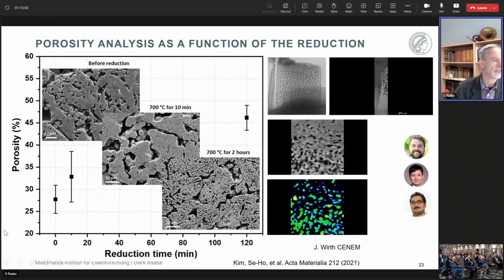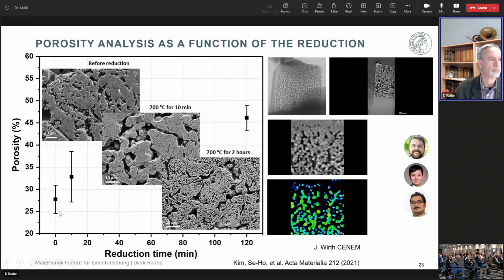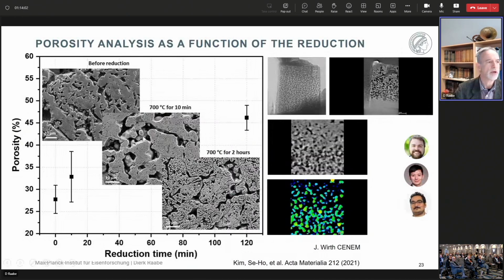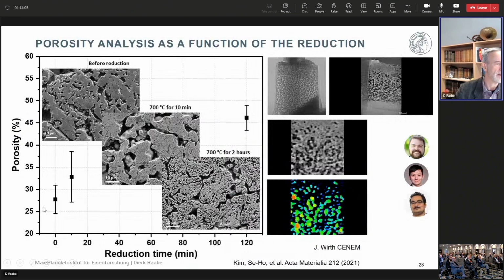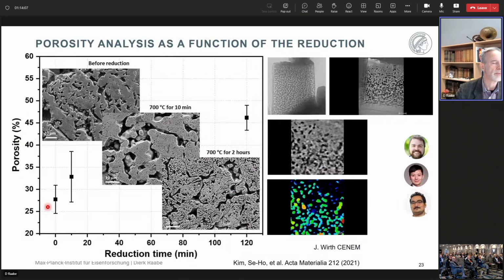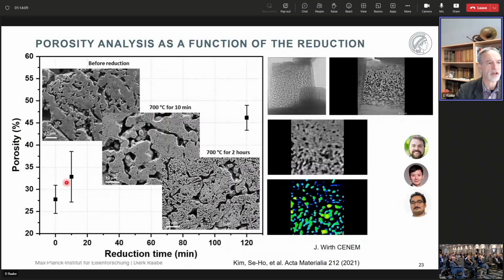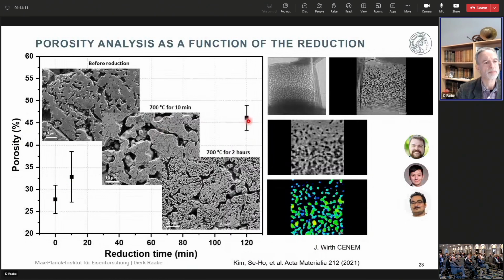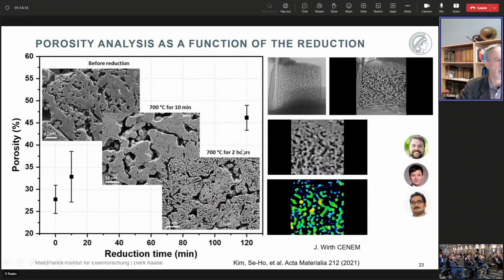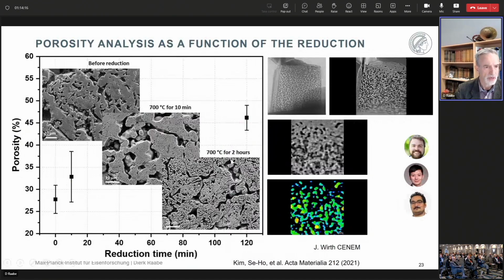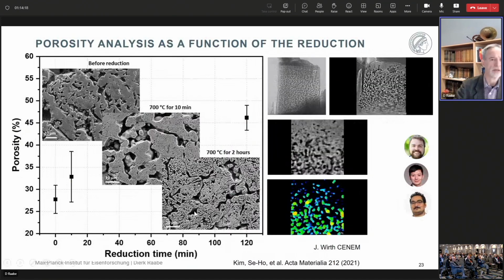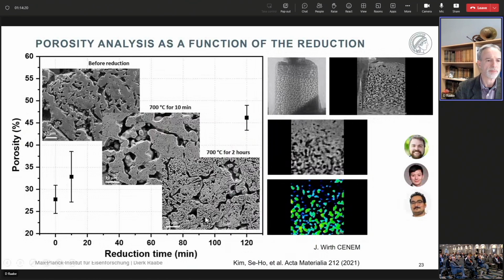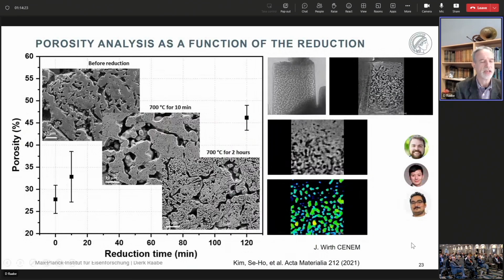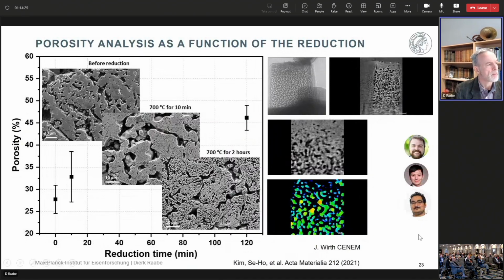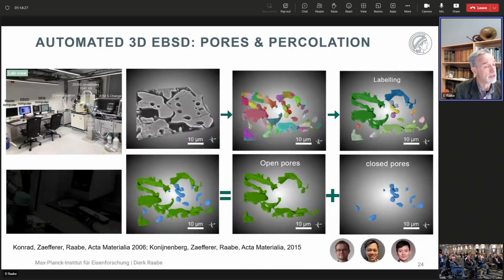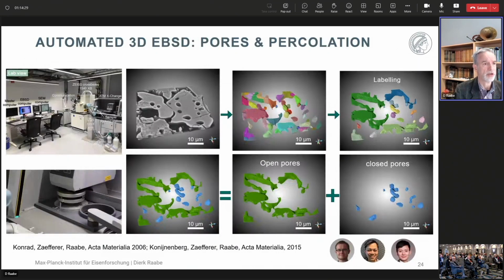This is the evolution of the porosity as a function of the reduction time, again at 700. So you see, you start with the inherited porosity from the sintering, and you end up with something like 45 up to nearly 50% porosity, depending on pellet type, during the reduction. And that is, as I mentioned before, associated with the mass loss, and we also do corresponding tomography on that in order to better understand the trade-off between the inherited sintering and the percolation porosity.